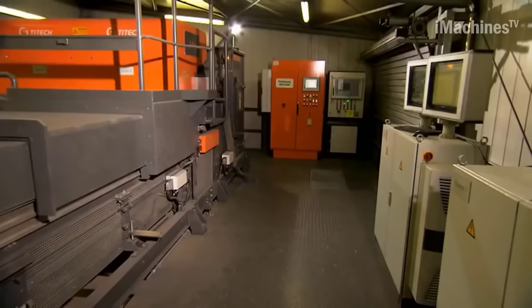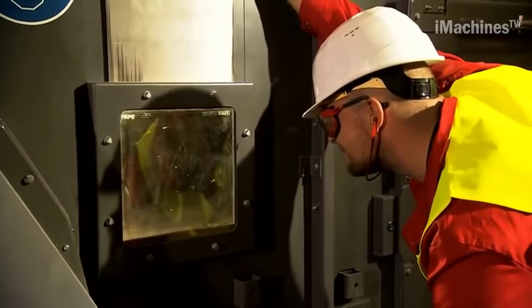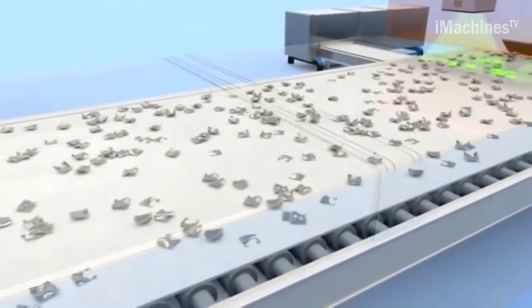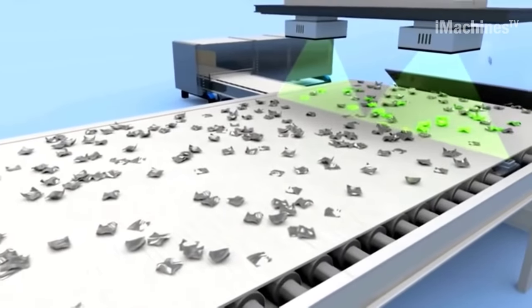The individual parts are examined by powerful X-ray sources with an energy of 160 kilo electron volts. To ensure worker safety from radiation exposure, the unit is covered with a robust lead shield. The aluminum chips are spread evenly on a wide conveyor belt, with X-ray lamps inspecting them from above.